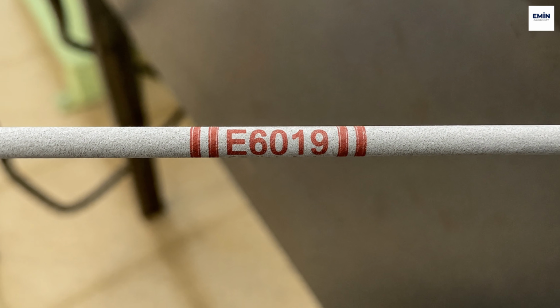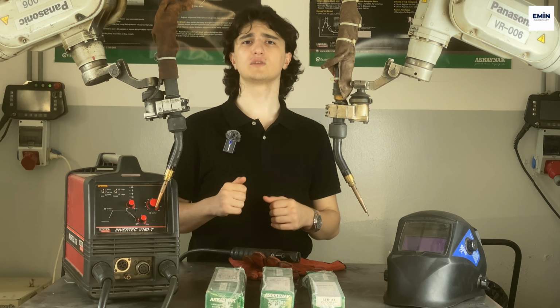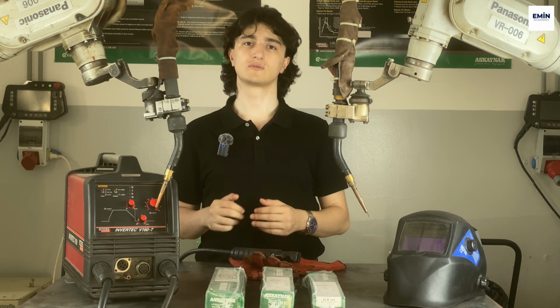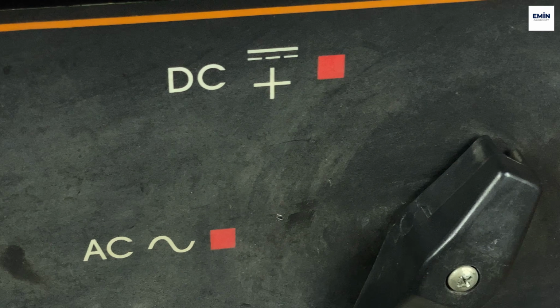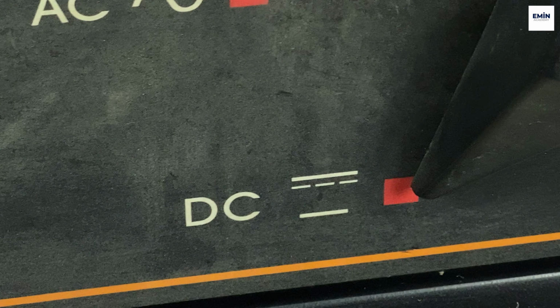9. Ilmenite-coated electrode. The E6019 electrode is an example. It provides medium penetration and the arc character is more controlled. It is not very common in daily use. It is suitable for AC, DC electrode positive and DC electrode negative polarity.